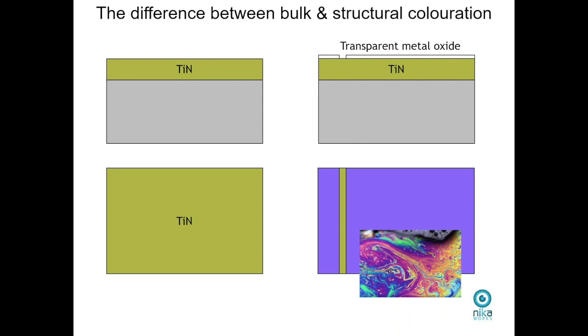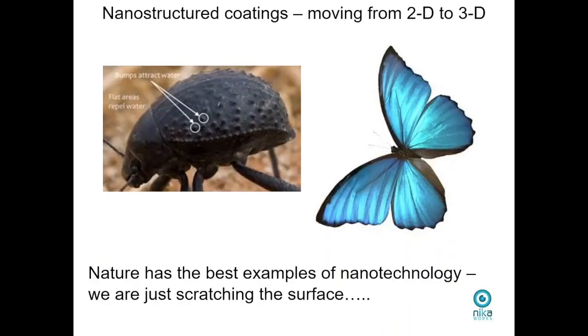If you put oil onto water, you get an interference with light, and the coloration of that reflection depends on the thickness of that oil film, and that's exactly what we've done with this PVD coating. That's great and it looks nice, but if you change the angle that you're looking at the oil, the color changes. Same with an instrument. If you look at that coating, which is blue, change the angle of view, it will change color. And also if you make a very slight indentation or scratch in that coating, the color will change. So it's not really suitable for instruments which will see some mechanical abuse. So that's a kind of adding a bit of 2D onto the coating. The rest of the presentation, we're going to move really into the world of nanotechnology.